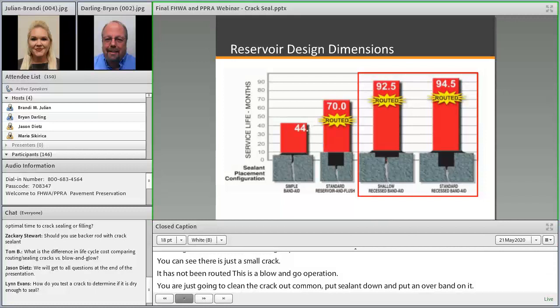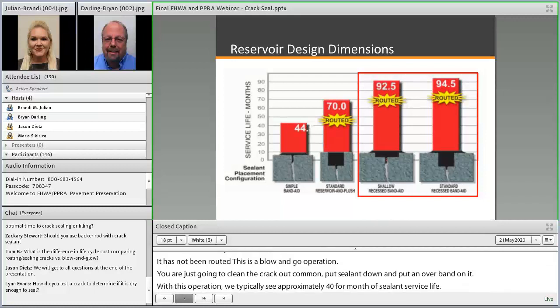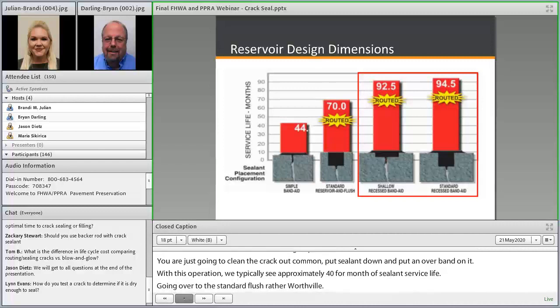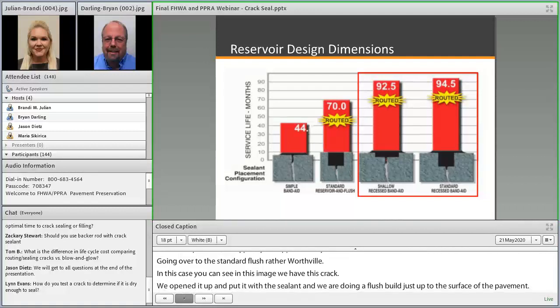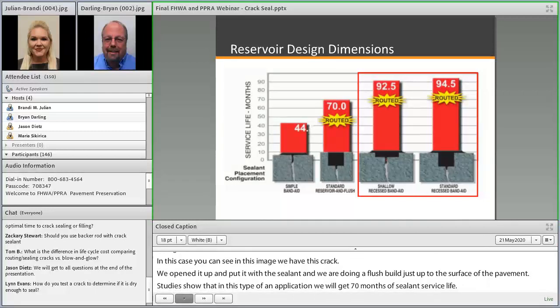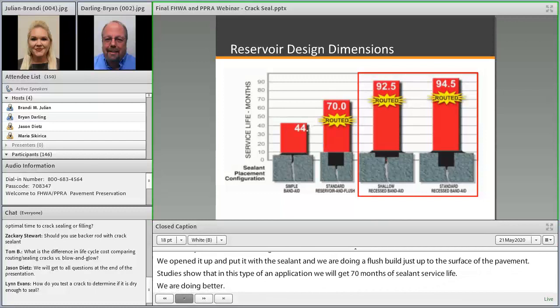Going over to the standard flush reservoir fill, so now in this case you can see in this image that we have routed this crack. So we've run a router on this crack, opened it up, filled it with sealant, and we're doing a flush fill just up to the surface of that pavement. Studies show that in this type of an application, we're getting 70 months of sealant service life. So we're doing better.